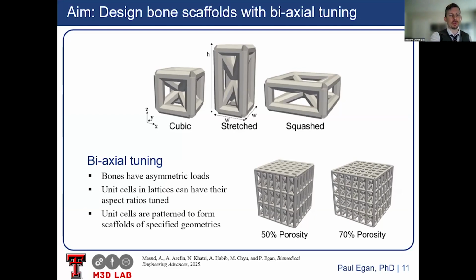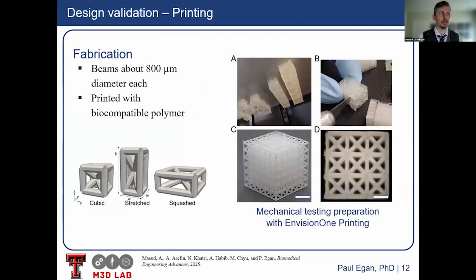And so we'll try this at a 50% porosity and 70% porosity, which is similar to what bone porosity is. And the main trade-off with porosity is the more porous it is, means you have more space for tissue to grow, but you have less material, so it's going to be less mechanically strong. So what we want to do is get something that's as mechanically strong as possible, but still supports tissue growth.